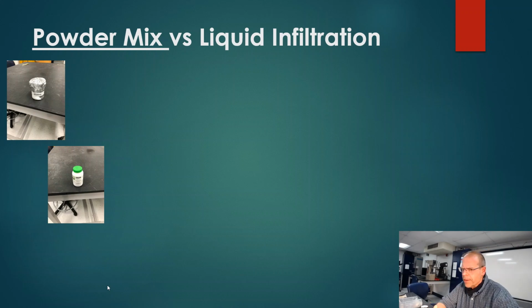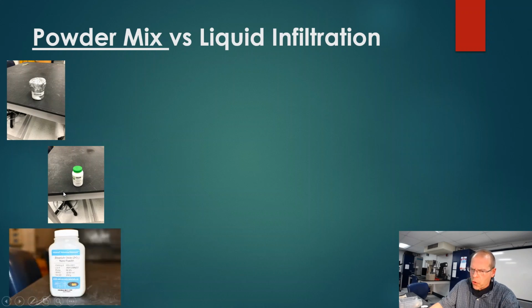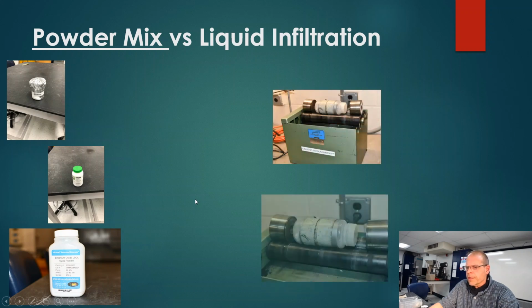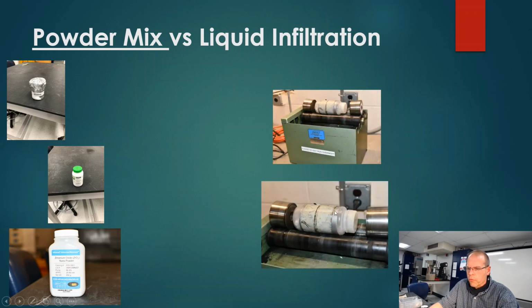We don't have to worry about it mixing up anything or adding anything, because when we heat this stuff up, it should evaporate right out of the little bit we use. And we're going to take some zirconium oxide powder. Alumina, zirconium oxide, a little bit of polyvinyl alcohol. And we're going to mix this stuff for 24 hours in a jar mill. We're going to roll it around.